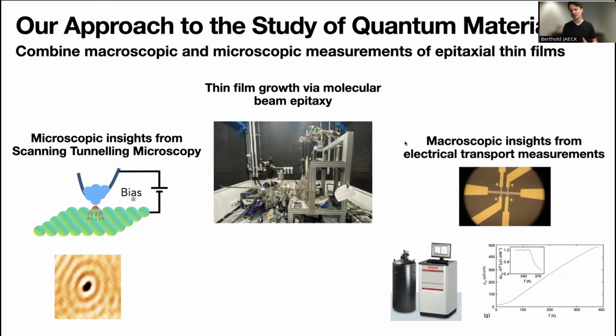And so what we have been doing here in Hong Kong is to set up a relatively unique thin film growth combined STM system that combines an MBE, which basically can grow any type of film you want, with a low temperature scanning tunneling microscope system. With the system we have here, we can grow thin films either for STM measurements, but also for device fabrication, that essentially allows us to study both the electrical transport properties of these thin films and also the local electronic and magnetic structure using STM measurements.